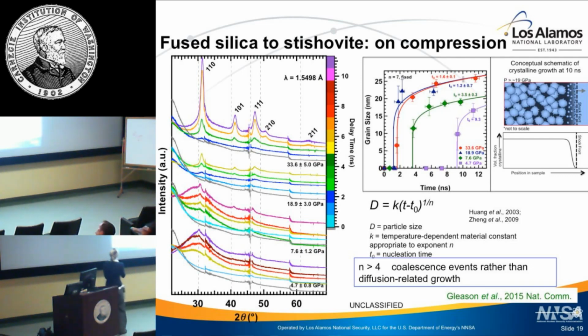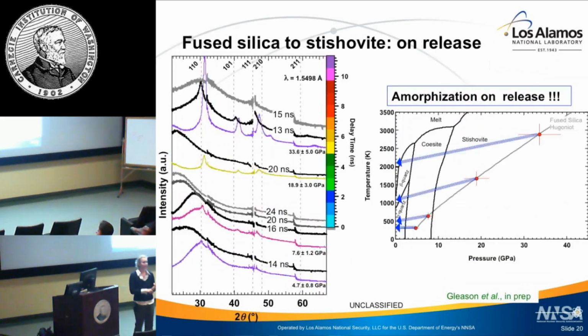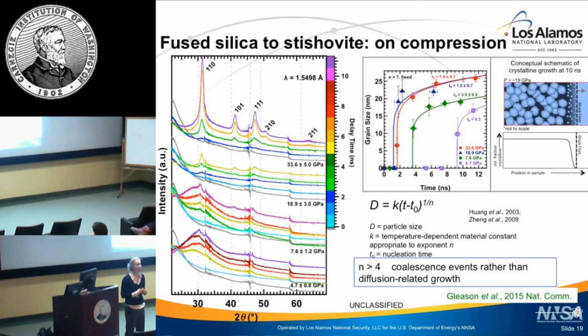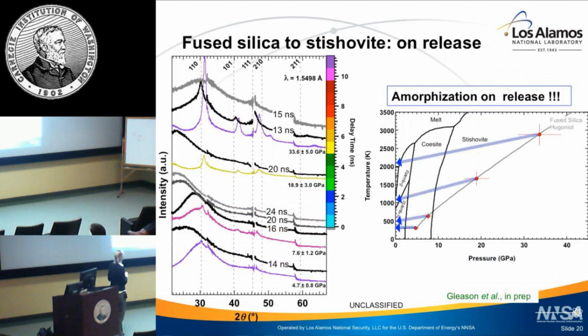So here I show again on the left, intensity as a function of 2 theta. We still have our clusters of pressure here. The colored traces are the highest pressure that I just showed, but in gray and black, now we're looking at later time delays. The laser has turned off, okay, and we're starting to release from the upstream side. And what we see remarkably is that there's a diffuse feature that comes back almost immediately. Almost immediately, we are reverting back to our diffuse amorphous state. It takes a little bit longer. We hold on to our crystalline material a little longer before we get our diffuse pattern back, even at the highest pressure.